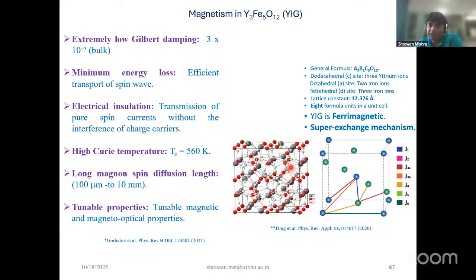Now coming to the material part. As I said, we have used garnet thin film as a base material, and the reason for that is this is a well-studied material, and here iron can occupy various sites, so they can go to the dodecahedral, octahedral, or tetrahedral site. So all different types of atoms are available with various coordination, and the lattice constant is very high, so 12.376 Å, which is generally 12.36 Å. It's like one order of magnitude higher.